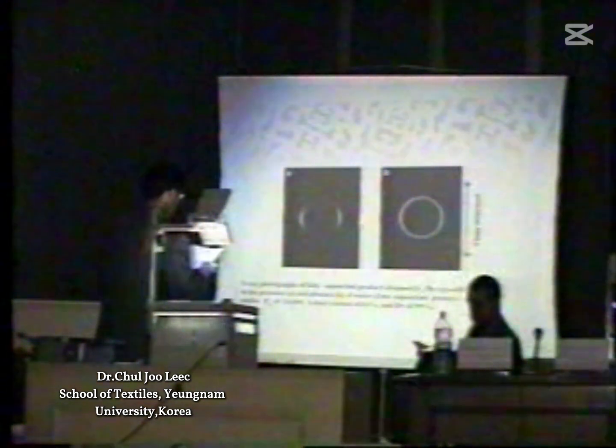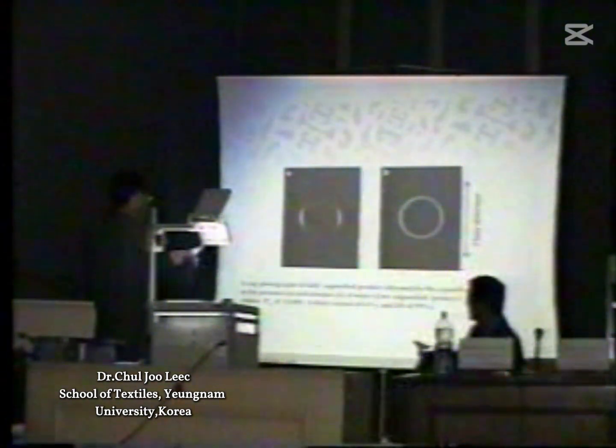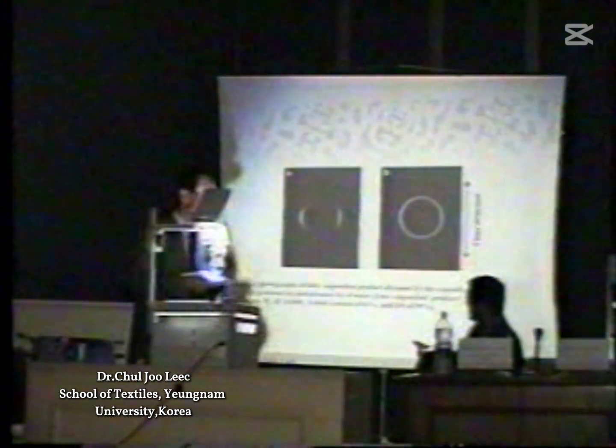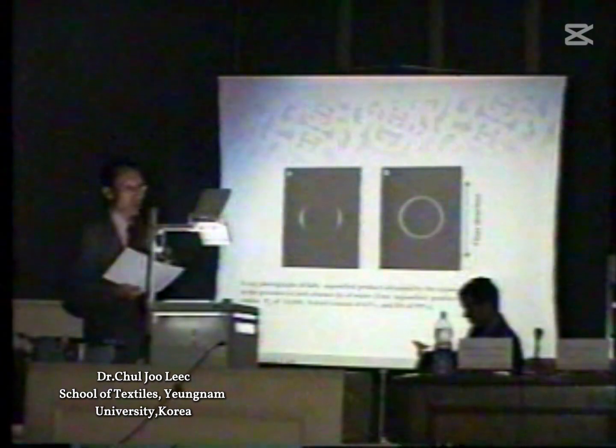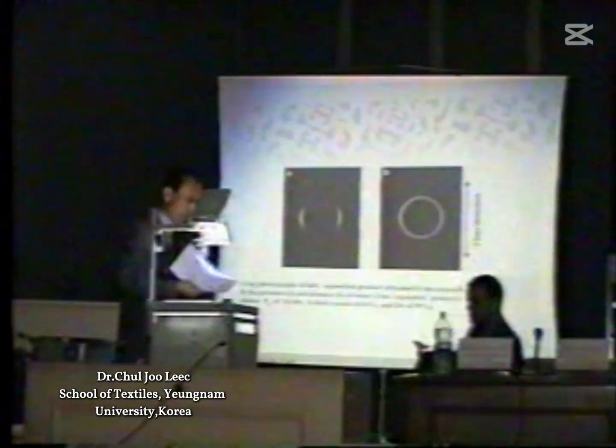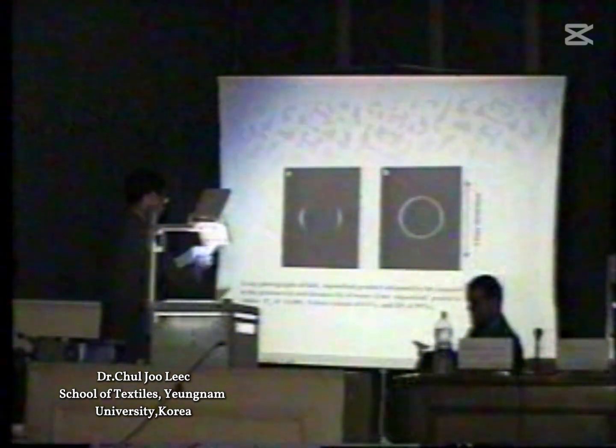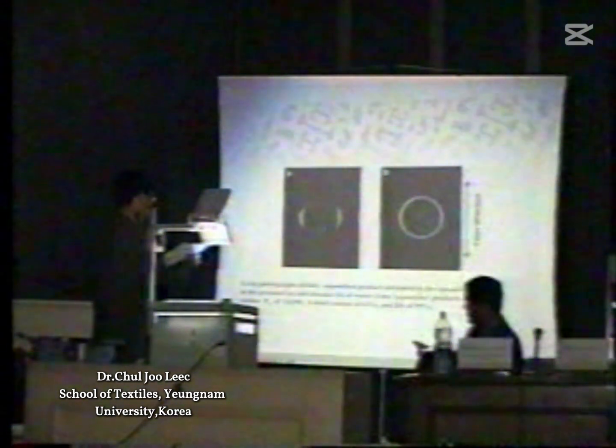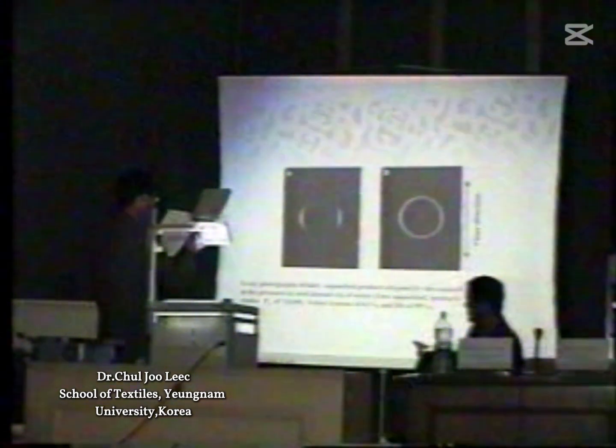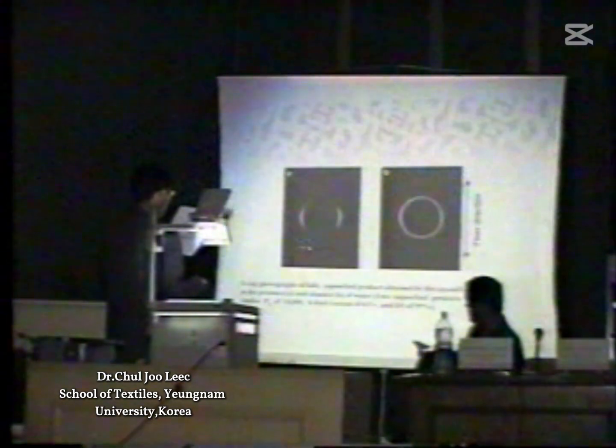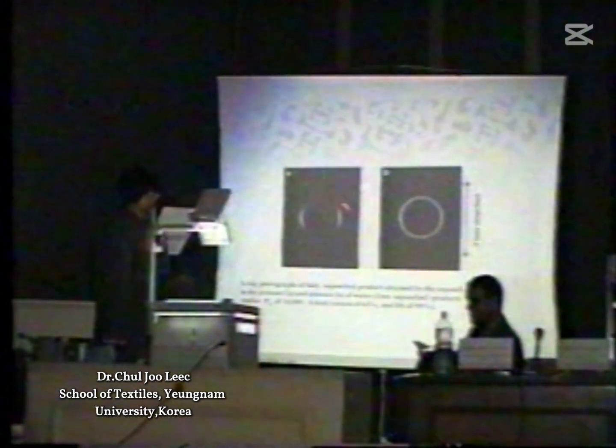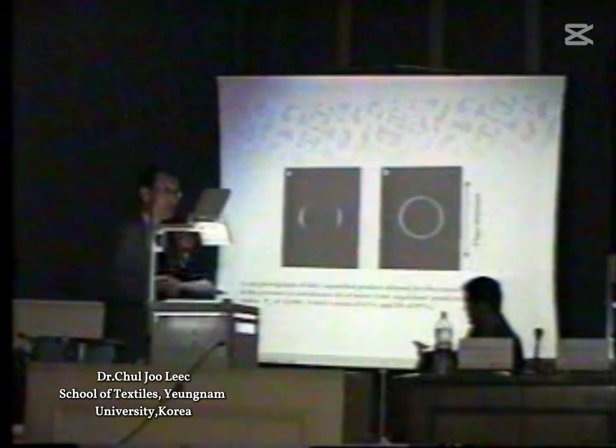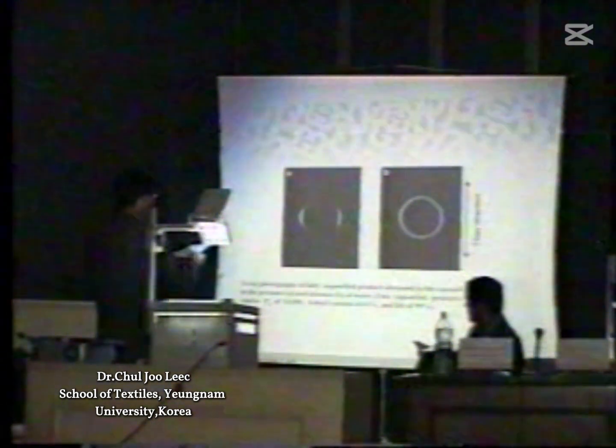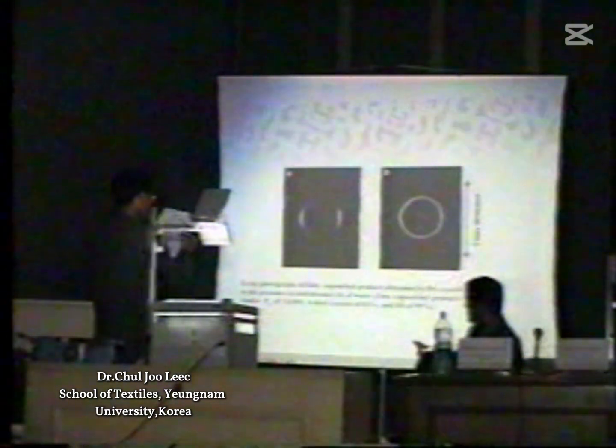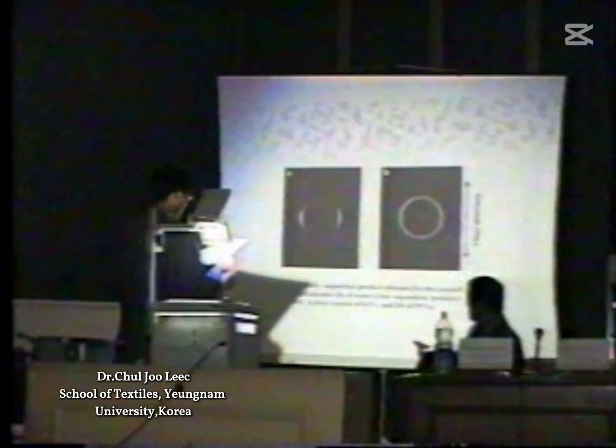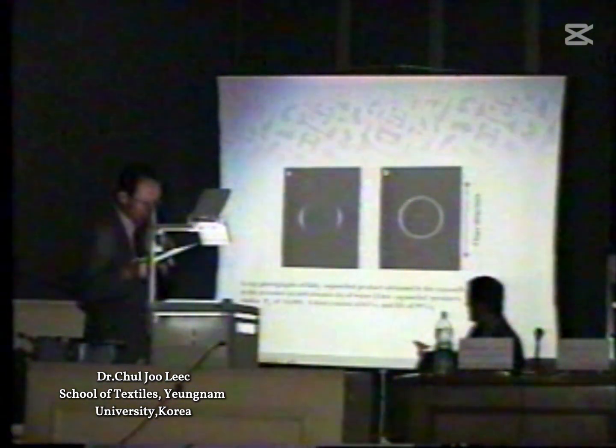From this slide, we can see the role of water during saponification. As you know, the solvent of saponification is methanol, but sometimes we did saponification with the addition of some water. Very interestingly, the existence of water is very favorable to obtain the fibrillar structure. Figure A shows the highly oriented pattern of polyvinyl alcohol fibrils, which was obtained under the medium containing water. It means the medium is methanol plus water. And figure B shows no orientation, for the polymer obtained in a water-free medium, only water-free methanol.